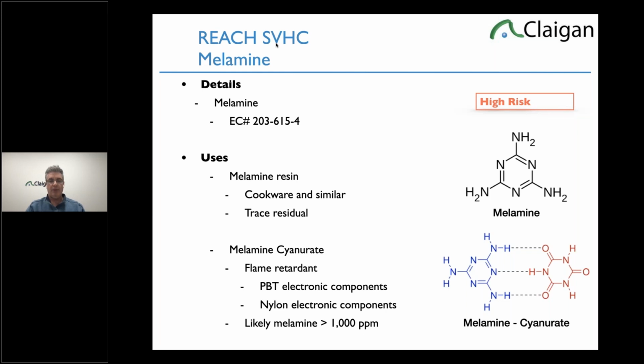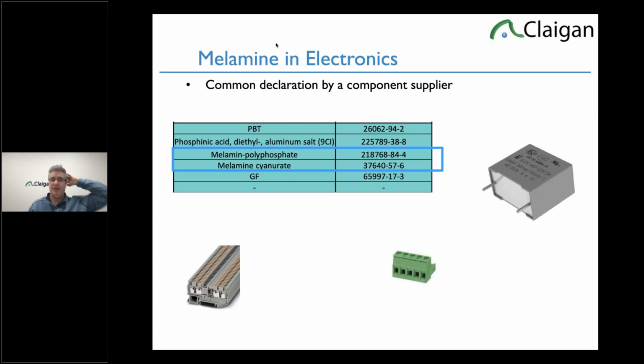So we see polybutylene terephthalate, PBT, and nylon electronic components use melamine cyanurate all the time. Those are hard parts in electronics. Some good examples, this material declaration for the part on the right, capacitor, that's melamine cyanurate, and it's also melamine polyphosphate, which probably degrades a bit into melamine too. Whether it's over 1,000 ppm, that's a good question, but they all use a melamine-based flame retardant, as do the terminal blocks down below.